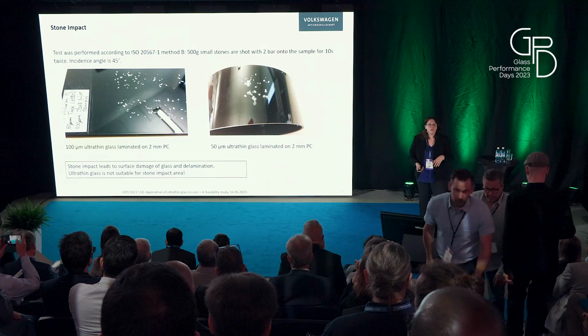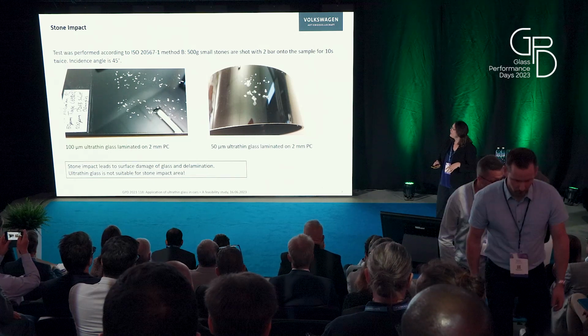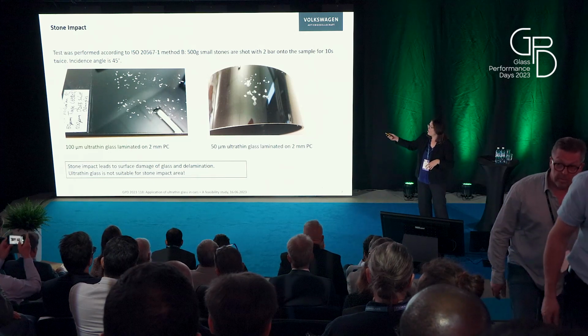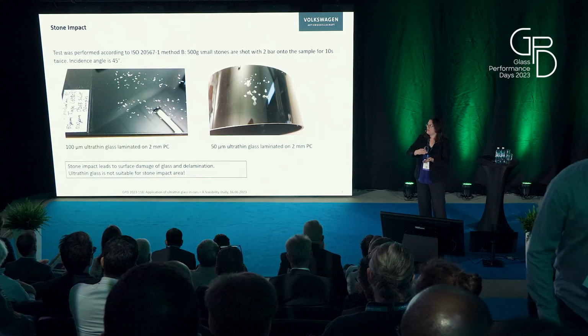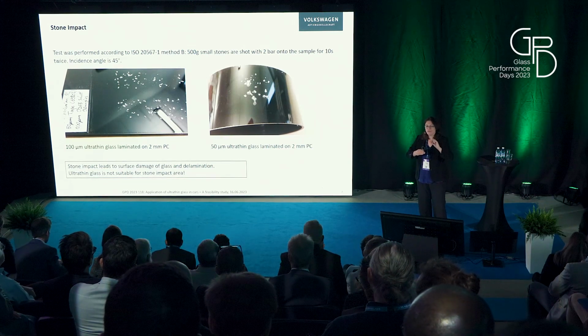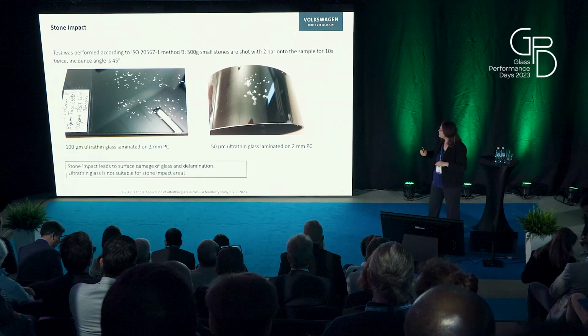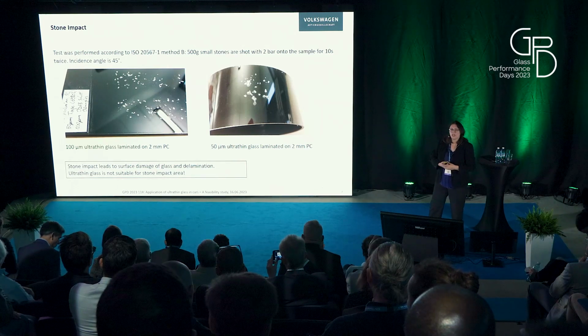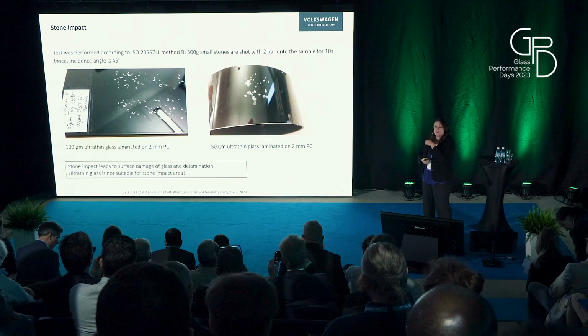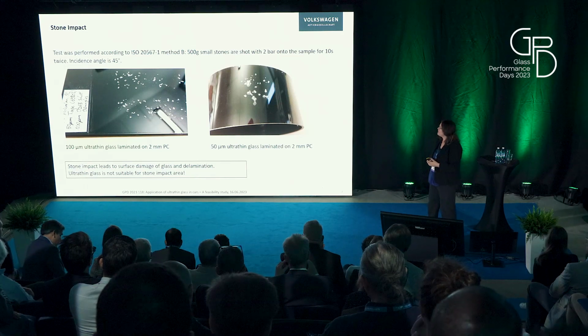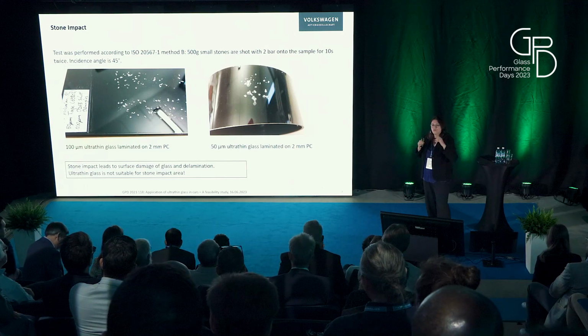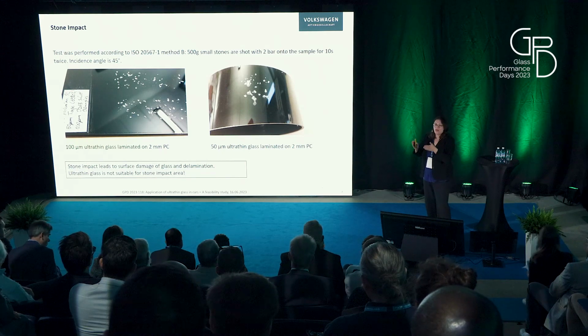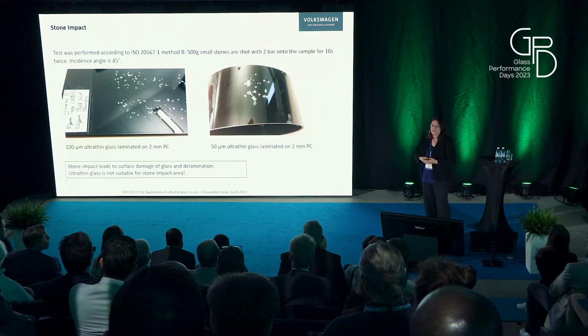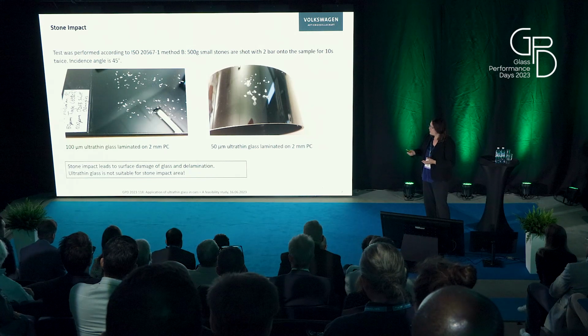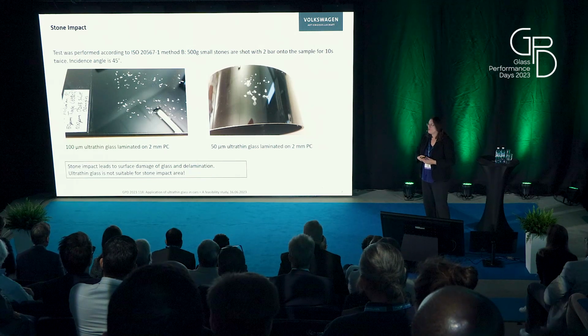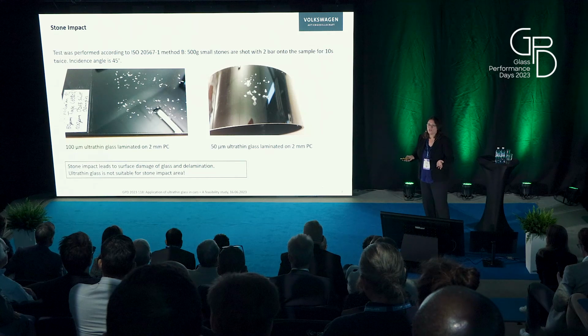So let's start with stone impact. Here you see a flat sample. So it's 100 micrometer glass laminated by a 50 micrometer thin acrylic tape from tesa to 2 millimeter polycarbonate. And we already heard this morning how stone impact test is working. So you shoot small stones, which are quite sharp, with 2 bar onto that sample. Angle is 45 degrees. And then you see the image. And unfortunately, the glass is damaged. So it's not really surviving.